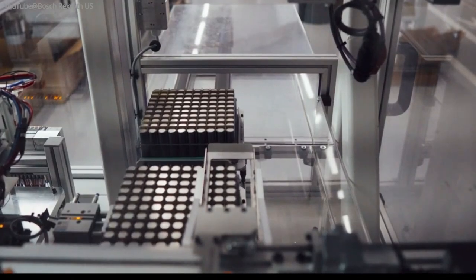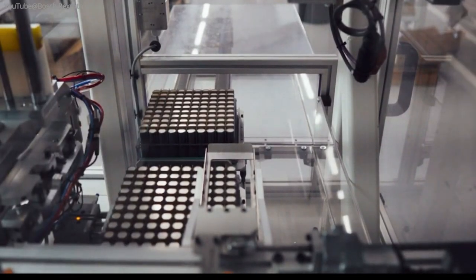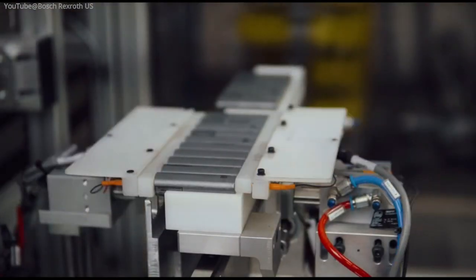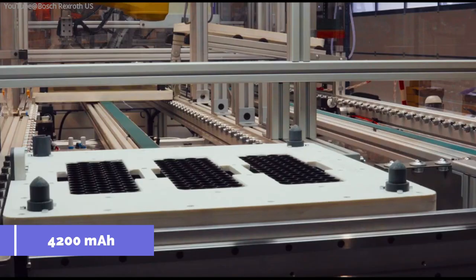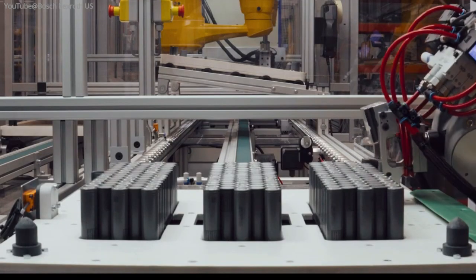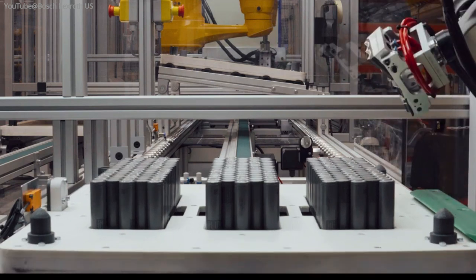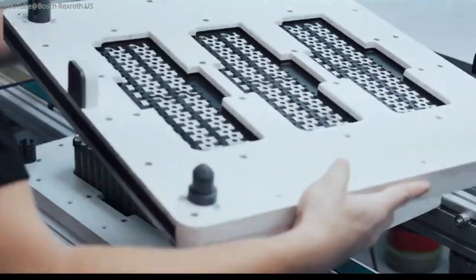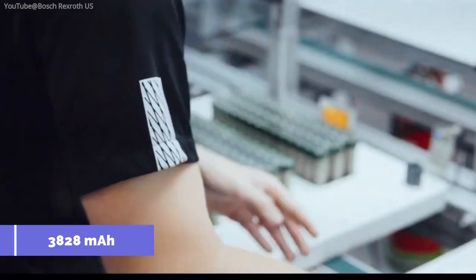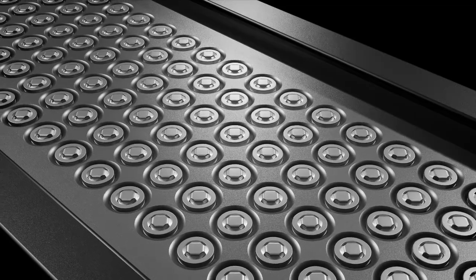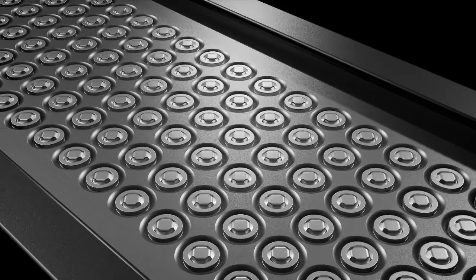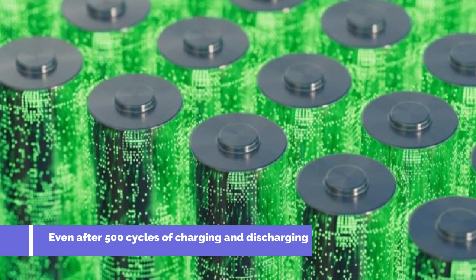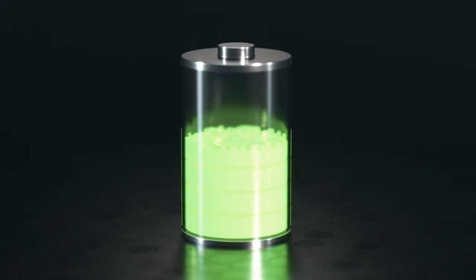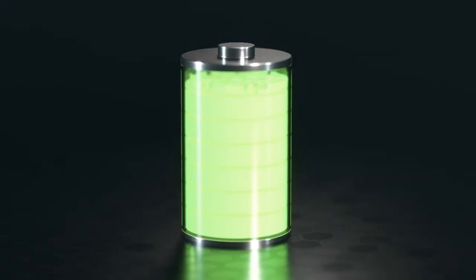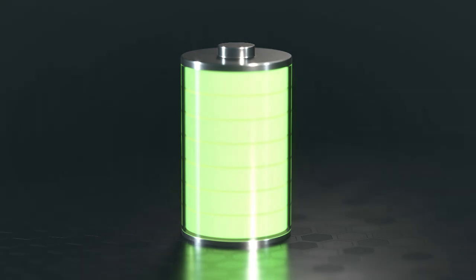In fact, silicon batteries have achieved the highest capacity when measured by weight, with 4,200 milliampere hours. This is significantly higher than lithium, which has a capacity of only 3,828 milliampere hours. Furthermore, silicon anode batteries retain 80% of their capacity even after 500 cycles of charging and discharging. They allow for faster charging and discharging, thereby improving energy density.